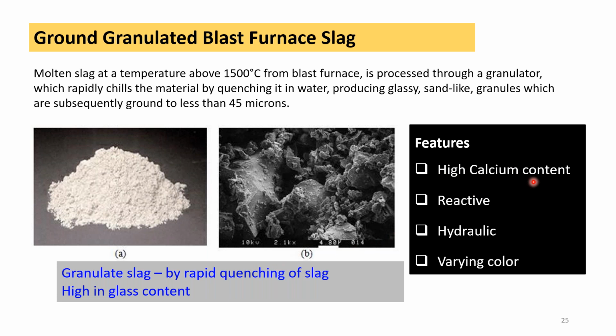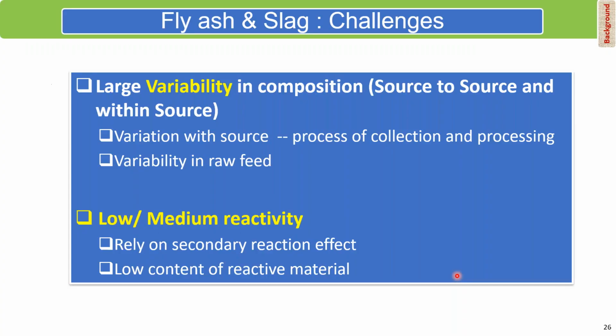That means it is self-cementing. If I add water to it, it is typically hydraulic in nature. It is reactive, not as reactive as cement, but certainly more reactive than fly ash. The only issue here is that it varies in color, and that sometimes makes the use of blast furnace slag in cement a little tricky because of the different colors associated with the slag.